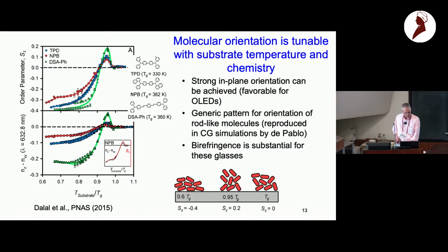Why not crystals? Partly because they have rough surfaces, which is bad. You get pinholes, and then the charges find a way of recombining without light coming out. Partly because they're polycrystalline, and that makes one pixel different from another. And so those are probably the main factors.